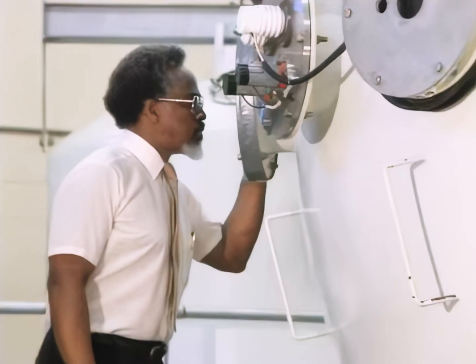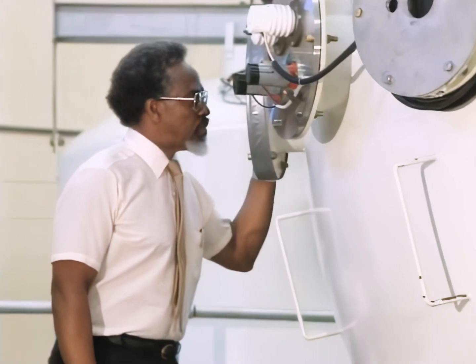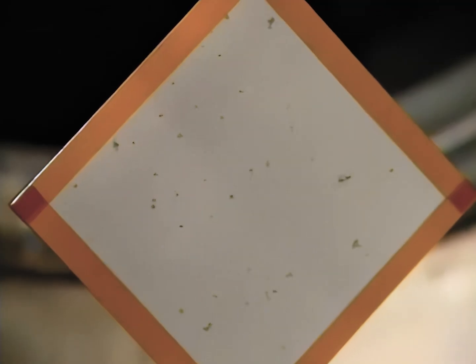If arcing occurs, it can cause tiny holes in the anodized surface and change its properties — in particular, its thermal properties, so that it wouldn't maintain the right temperature. In addition, material that comes off during these arcs will deposit elsewhere on the space station. The solution to the possible arcing problem, it is believed, is a device called a plasma contactor.